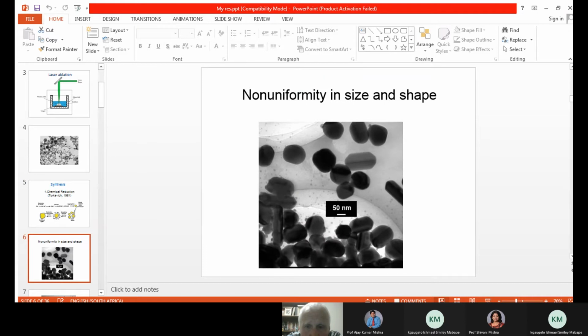When we tried to repeat the result of Turkevich and observed our result by electron microscope, we observed something like this. The result looks not bad, but not so beautiful. We again produce a mixture of large particles and very small particles. Very small particles of a few nanometers, and very large particles, 200 nanometers, something like this. So we need to do more. Okay, let's move to the next slide.